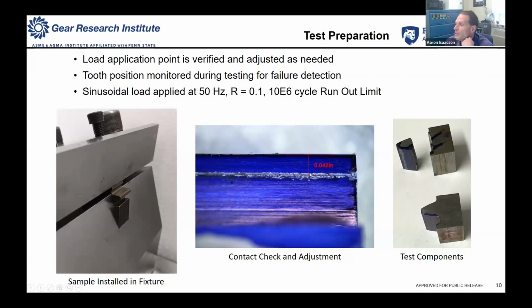We check our contact pattern, right? So here you can see most of the face width of a tooth. We'll put layout bluing on it while it's in the fixture, and then we'll apply several cycles of load to make a pattern. And again, you can see what it looks like. It's very much a line contact across, as you would expect from a flat piece of tooling contacting that. And we can use these measurements. Again, we can tweak it by shimming things up and down to control where it contacts, but we can take this number and put this into our bending stress calculation so we can actually compute actual bending stress based upon the point we're applying the load.